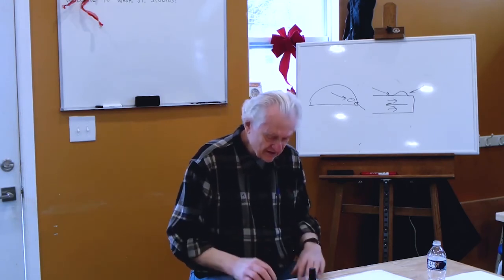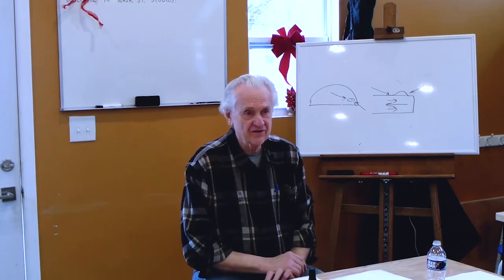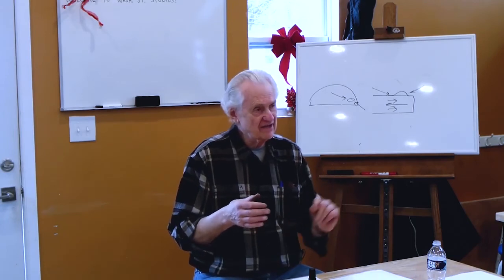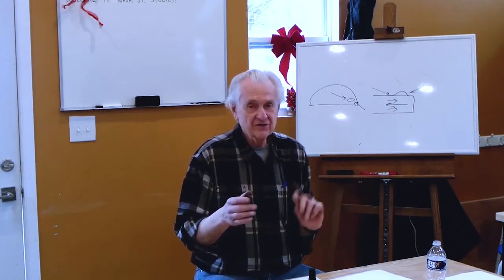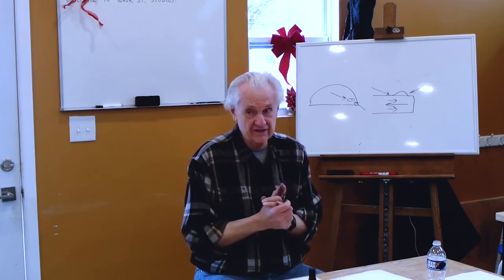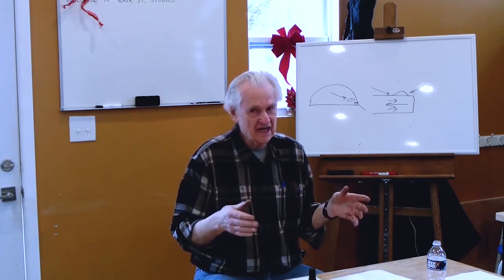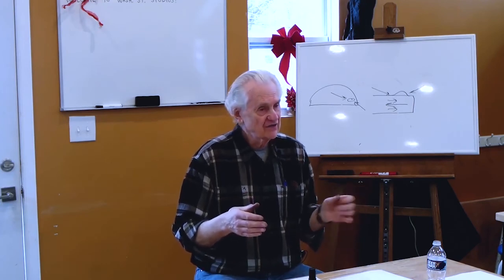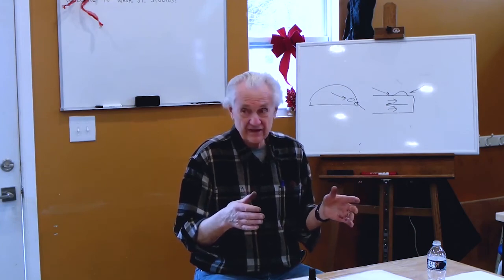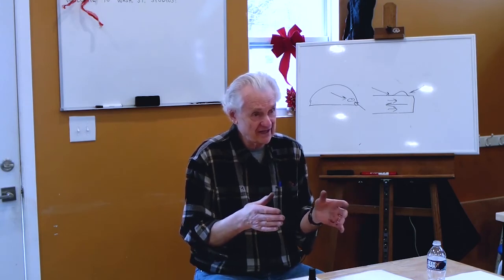And the last thing I wanted to talk about here is the ideal condition for a glaze, and you've probably heard of this, and this is why it works. Ideally you'd like the clay to have a slightly higher coefficient of expansion than the glaze. Okay, I'll repeat that. You would like the clay to have a slightly higher coefficient of expansion than the glaze, so that when the glaze is cooling, the clay contracts slightly more than the glaze, right? Everybody with me? So it puts the glaze in compression. It squeezes the glaze, right?